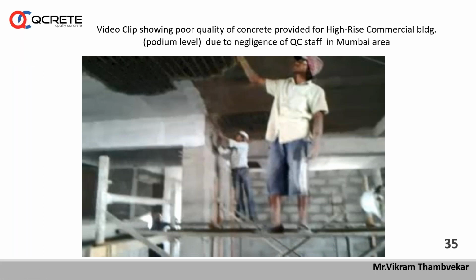With the help of this video, you would have observed the concrete which was supplied at site was not proper. But generally people check only these slump values, and they say the concrete is okay. But I want to tell you, if you observe the fresh concrete like this, when your concrete looks very whitish and not a grayish one, then you should raise a doubt. It may contain a high amount of fly ash or something. And if it is more darker, then you can judge there may be use of other material like GGBS or something in large quantity.